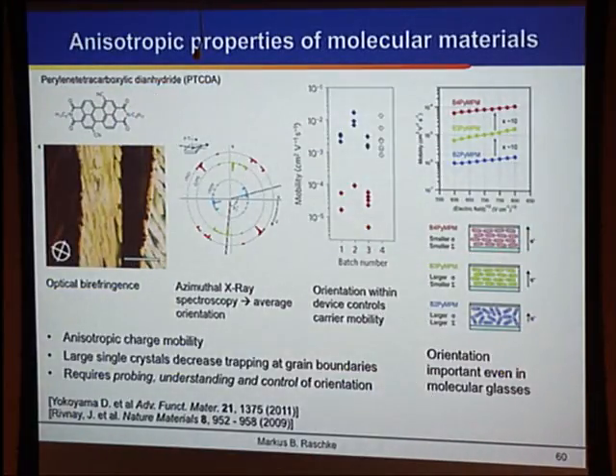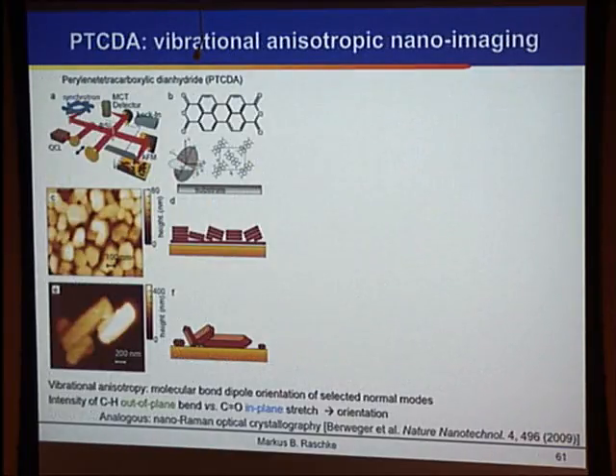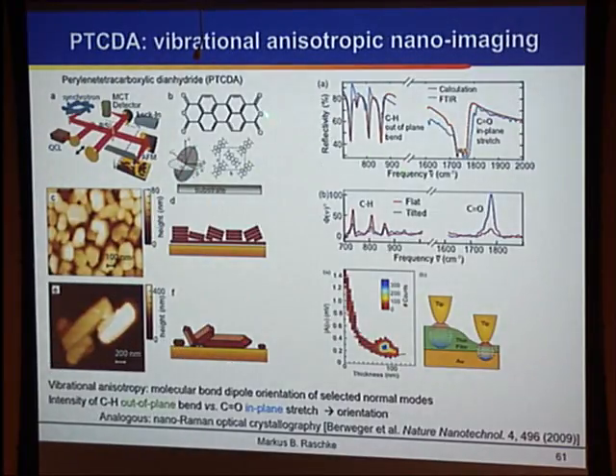We can do this then also in molecular electronic systems, where we can see in these types of two-dimensional molecules where it's very sensitive, depending on the stacking, in which direction you get electron transport. And so there's a lot of problems associated with the disorder in these molecular electronic systems, built in this case out of these PTCDA molecules. And so here's a good example where, by looking at the transition dipole moment, again probing the carbonyl, which is in plane, and then there is an out-of-plane motion of the carbon atoms of the CH mode on the phenyl side. And so by looking at the ratio of the CH versus the carbonyl, we can reconstruct the orientation and really the Euler angle of these molecules under the tip.